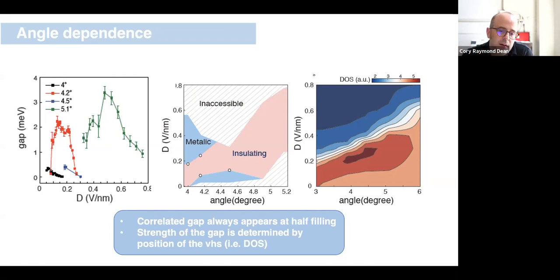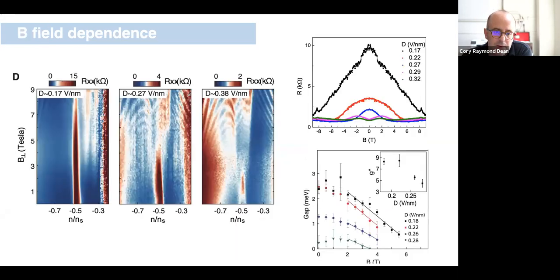We interpret generally as telling us that these systems, at least in this angle range that we're studying, are maybe in a regime of moderate interaction strength. So we have this scenario where we have something that's a Hubbard-like model. We have a triangular Moiré pattern. And we see that when we reach half filling, a correlated insulator emerges, but that insulator is tunable with density of states, essentially, which is what we're tuning by tuning the Van Hove singularity, which again suggests we're in some region of moderate interaction strength. We're not very strongly interacting, and we're also not very weakly interacting. That's at least our interpretation.